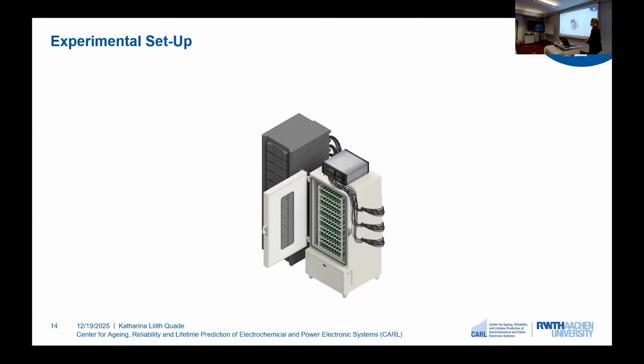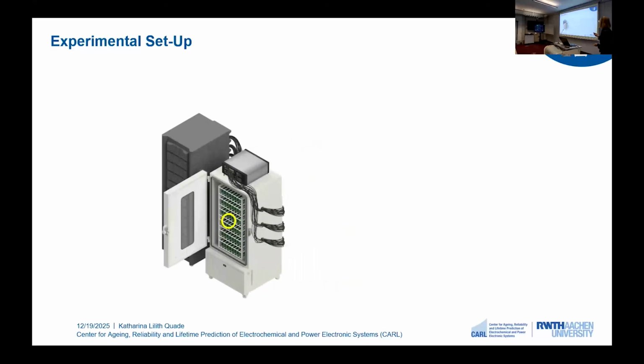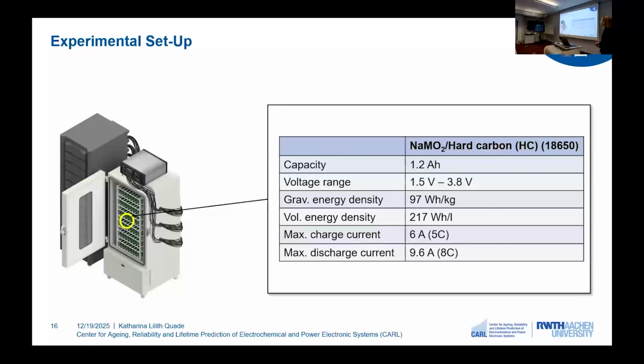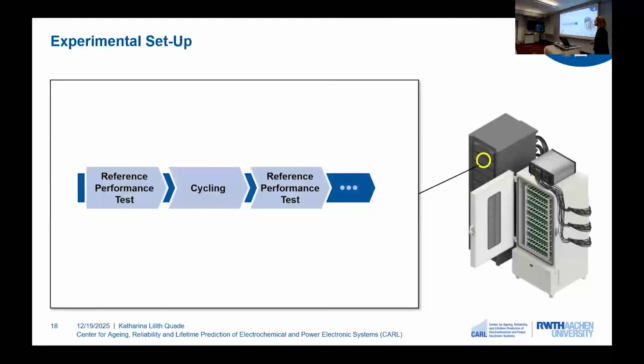We have a temperature chamber that is operated at 25 degrees Celsius. We have a cycler here on the left for the charge and the discharge of our cells. And we purchased cells that feature a layered oxide cathode and a hard carbon anode. And here again, we can see the characteristics of the cell. We have a capacity of around 1.2 ampere hours. We see we have a slightly higher energy density and we have acceptable current rates. So now we cycle the cells by alternating reference performance tests and the pure cycling.